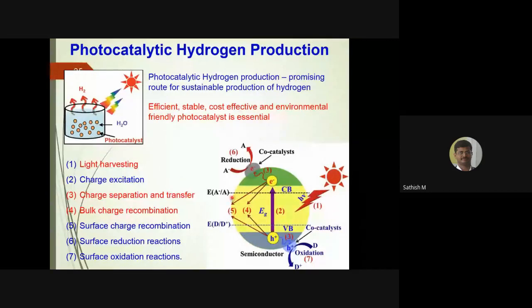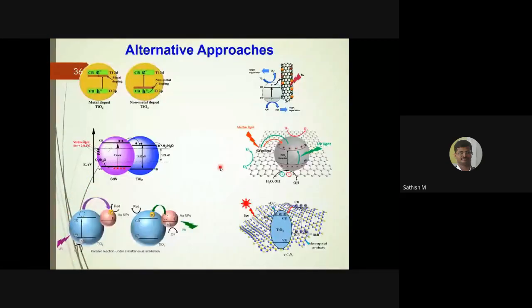You cannot avoid any such reactions. The only thing is you can make the desired reaction faster, so that the other reactions are minimized and you can increase the efficiency of the process. There are various approaches, such as using a co-catalyst or another semiconductor. Some of these approaches are metal doped or non-metal doped semiconductors, TiO2 coupled with cadmium sulfide, which is a coupling of two semiconductors, or combining TiO2 with graphene or carbon nitride. So the electron can be easily injected into the other system, the electron hole pair can be separated quickly, and you will not have recombination issues.